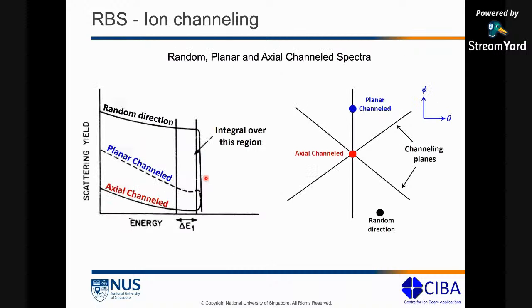And then when we talk of channeling, again, there are two kinds of channel spectra, depending on where you are on your atomic lattice. So let's imagine these to be the channeling planes. Okay, if these are the channeling planes, at the intersection of these planes, you have this axis of your channel. If you are able to align your incident ions exactly to this axis, what you're going to get is what we call an axial channel spectrum. Okay, so this is an axial channel spectrum where you will have a minimum backscattered yield, if you are right on the axis.